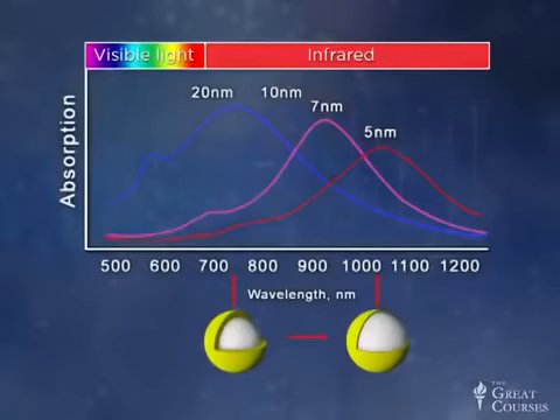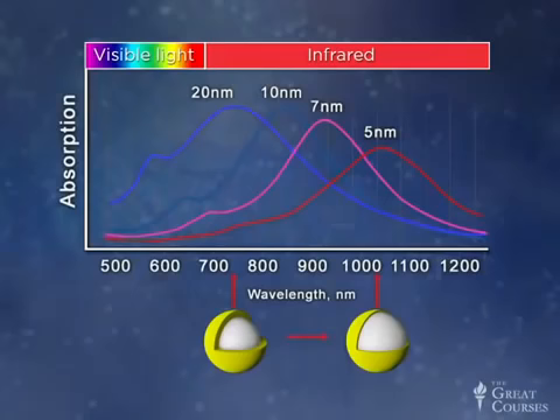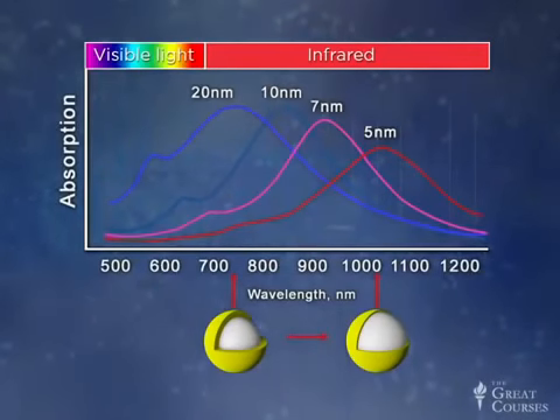It turns out that one way to solve the absorption problem is by making a modified type of gold-based nanoparticle. Several years ago, researchers at Rice University figured out that if instead of using nanoparticles entirely composed of gold, they instead used a core of another material, like silica, and then they coated it with a very thin layer of gold, what they observed is that this shifted the absorption of the particle way into the infrared. And infrared is a much better region of the spectrum for getting light to pass through tissue. The absorption by tissue is really minimal in this part of the spectrum, so the light can actually reach the nanoparticle.